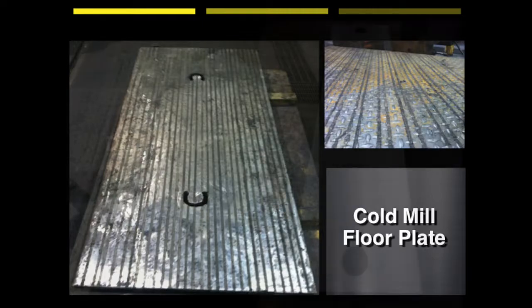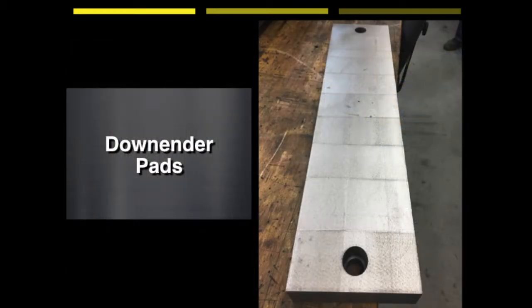A very smooth ESD coating was applied to down ender pads. And although not shown, these get finished with a top coat of ferritic nitrocarburizing. The ferritic coating seals the surface and gives added protection against transfer. This solved the pickup issue caused by the hot ingots rotating on these pads under very high pressure.